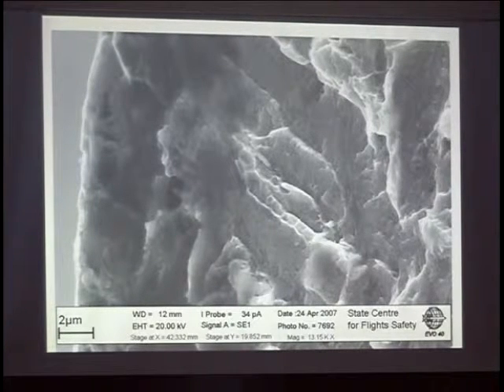So it should be clear that for all tests where we stopped our test to determine the fatigue limit, it will be questioned. Maybe it's not the same manner of material cracking that we think. Maybe with some more cycles, the crack origination would be not at the surface, but subsurface. So it will not be a point which indicates the fatigue limit. It's a point about our limited knowledge of the material's manner of cracking.